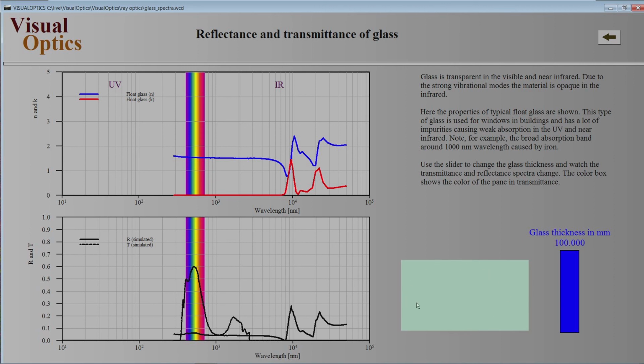Here is the visualization of the color, so of the transmission color. So what you see here is that the red light, due to the iron absorption, is decreased a lot. The amount of red light, the green light survives best. So light that has traveled through thick pieces of glass has a greenish appearance. Looks greenish blue, and this is what you can observe in any glass factory. If you have large piles of glass, it all looks green.